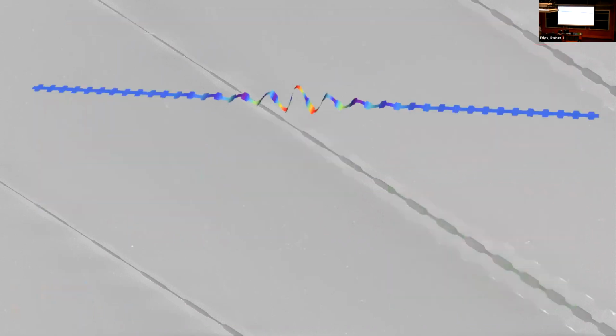So we were interested in studying the vibration of the violin modes, essentially, of this little nanomechanical beam. This is a picture of one such violin mode. It looks a little bit different than what you would normally associate with the mode of a string or a violin. You can see it's localized in the middle of the beam. And the reason for this is that these corrugations here are basically modulating the transverse stiffness of this beam. This is a 1D phononic crystal. And in the middle of this beam is a little defect in which the vibrational modes are localized due to this phononic crystal pattern.